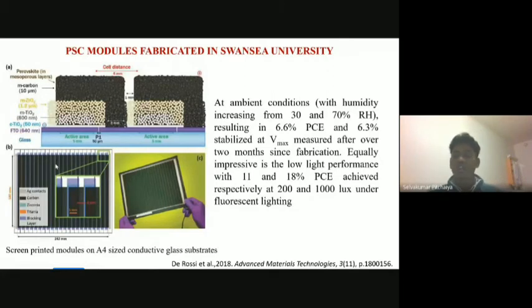Actually, sir, the substrate is not at all a problem. The thing is, you must have a highly transparent and highly conductive substrate. These two are the basic criteria, because when you are illuminating light from the other side, it must have the tendency to pass through the conductive layer substrate. In other applications, you can use non-conductive substrates, but in photovoltaics, particularly in second and third generation solar cells, you must have an optically transparent substrate, but not for wafer technology, because wafer technology works on the photoelectric effect, where even the silicon wafers absorb the light. But here you have various transporting layers in between the active perovskite layer, so you must allow the light to pass through the substrates.